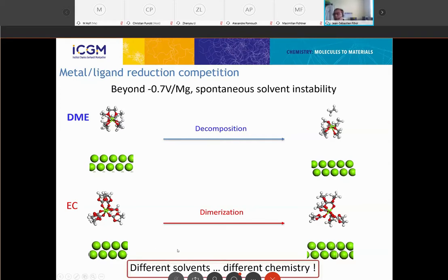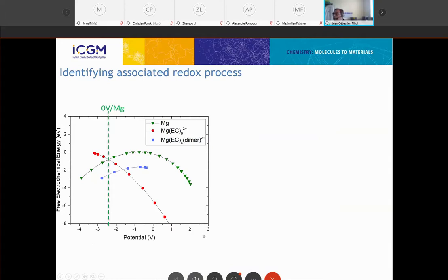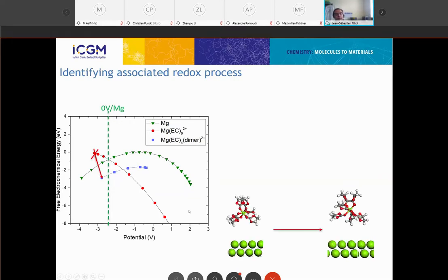So in this case, we observe that with these different solvents, we have very different chemistry. That could of course be somehow expected. Now, we really wanted to identify the associated process, this time not associated with the reduction of the magnesium, but with the reduction of the solvent molecule that is coordinated to the magnesium atom. And in this case, to start with, we look at the molecule in ethylene carbonate.